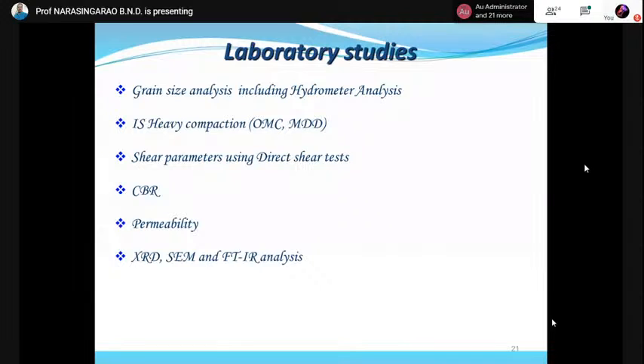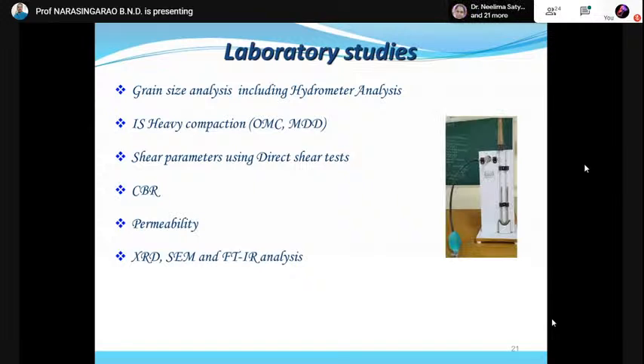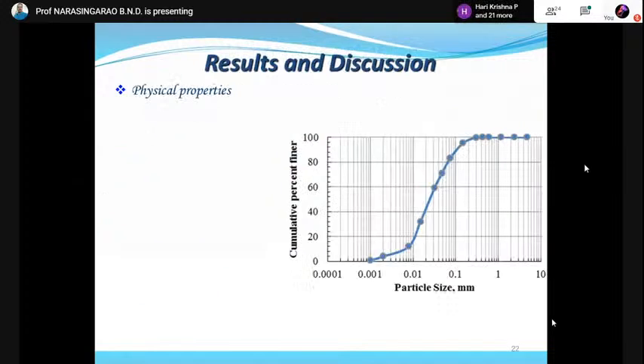And not only this, XRD, the scanning electron microscope and FTIR analysis have also been carried out. The specific surface of the fly ash is also determined using the Blaine's air permeability apparatus.